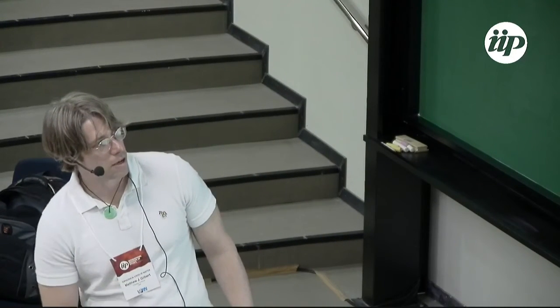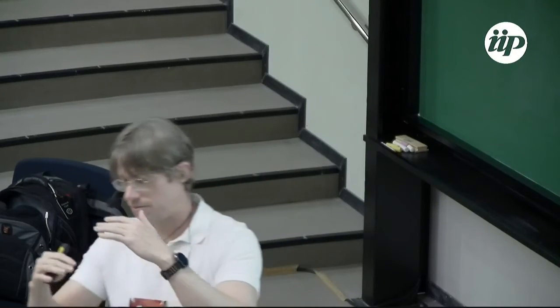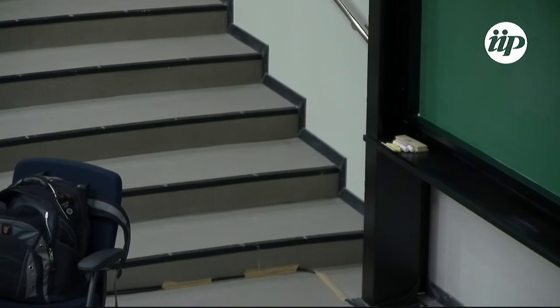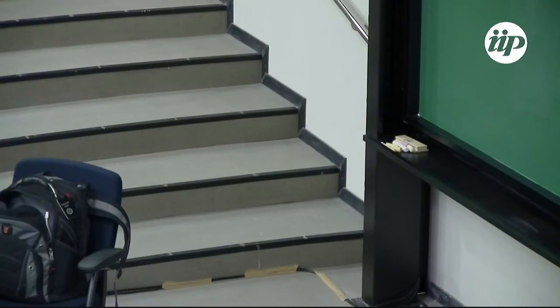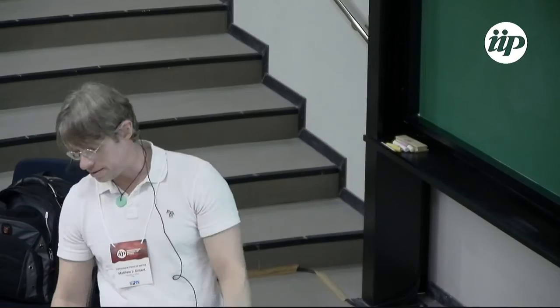And so you can sort of see, okay, well, we can back out from the experimental data and try and understand what's going on. And so for this, we saw that the mean free path for these bismuth selenide samples was about 16 nanometers. And so when you calculate the coherence length, it's about 23 nanometers. And so that explains more or less what we see in the bulk, but it doesn't necessarily explain what's going on in the surface. But to think about what's going on in the surface states and why they're decaying a little bit faster than the bulk states, you can think about it in terms of maybe a density of states argument, where I'm taking the surface states and I'm forcing them farther and farther apart. So it's a little bit more difficult to sustain superconductivity within the surface states as I continue to increase the film thickness.